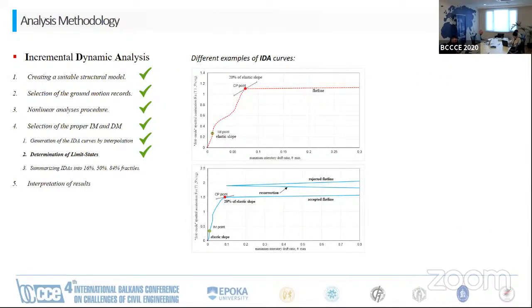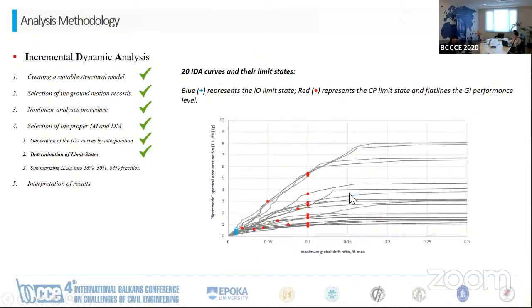For the last stage, which belongs to the global instability, it is actually shown by the flat line, or the horizontal line, in our graphs. And there might be different cases. For example, in the second case, we can see that we have at least two flat lines, which the software may give as these kinds of results, and then continue with the second or multiple flat lines. For these cases, we are going to reject all the other flat lines after the first one occurred.